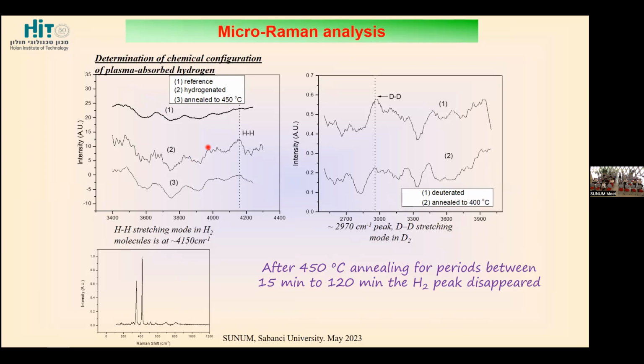Again, it was also chemically proved by micro-Raman, when we measured hydrogen molecular Raman bands, which is very difficult to measure, or deuterium bands in our structures. We also proved that when we anneal these samples to 450 degrees, these bands decrease, so they indeed are related to molecular hydrogen in our sample. This measurement was very difficult because the cross sections for molecular hydrogen are very low in Raman, so we needed very long measurements. But anyway, we succeeded to do this and to prove our findings.